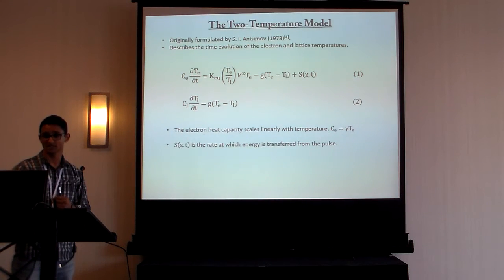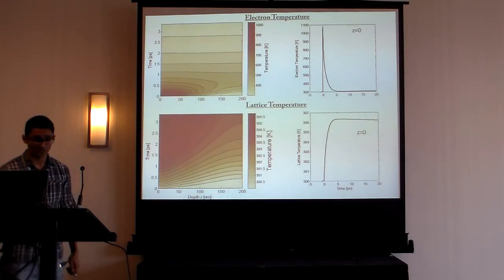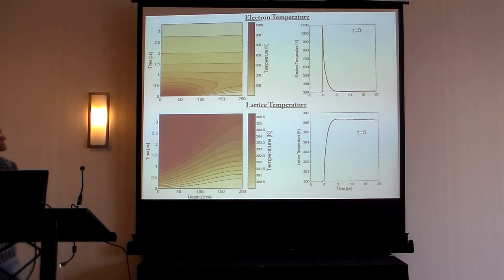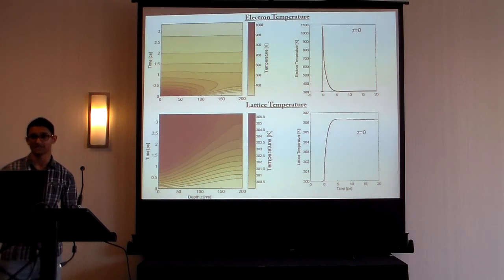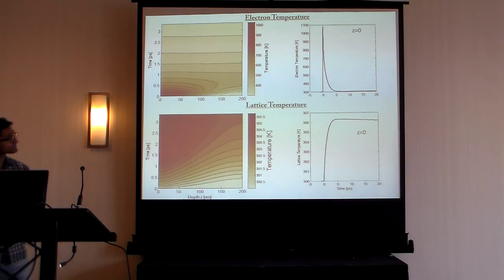So solving these simulations numerically, we get results like these for electron and lattice temperature profiles. And one thing to note is that the change in electron temperature varies on the order of 1,000 degrees Kelvin, whereas the lattice temperature changes by roughly 5 degrees Kelvin. And this is due to the large difference in heat capacities between the two.